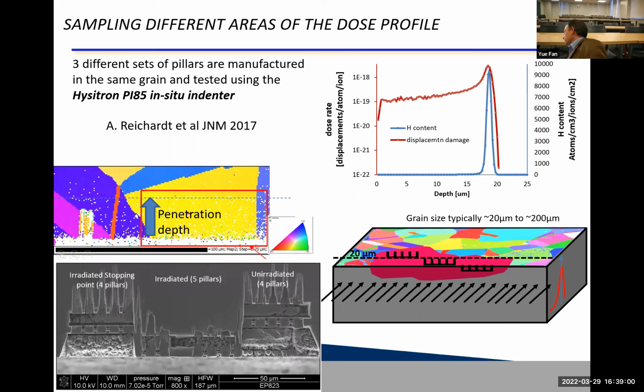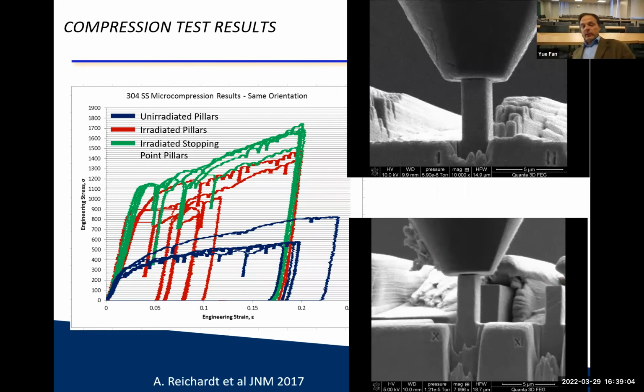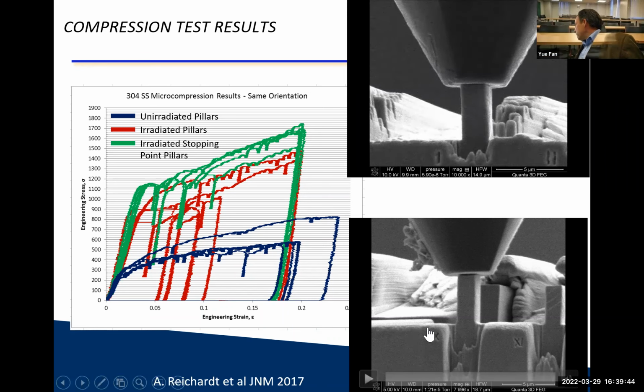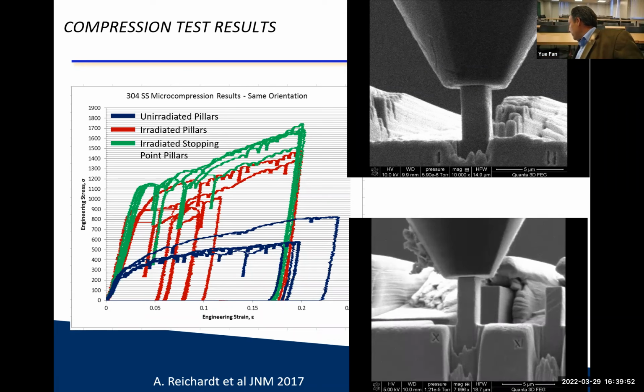That's what that looks like in real life, but that's not really all that exciting. So let's look at these pillars. This is obviously a little bit older data. What we look at is the stress strain curves on the left side. Here, stress strain of these pillars, and this is unirradiated, irradiated, and this is irradiated, but at the stopping peak, right where the peak is, around there. And so the top movie here shows you an unirradiated pillar. What we see is nothing too exciting. We just squish that thing. It gets a little bit bigger and a little bit shorter. But the irradiated version is interesting. There we see actually a white line popping up here somewhere and another white line popping up there somewhere. And we see that the geometry doesn't change much as a whole, but with the sudden deformation, there was a little sudden jump, and now this white line is increasing, and there's another one popping up.